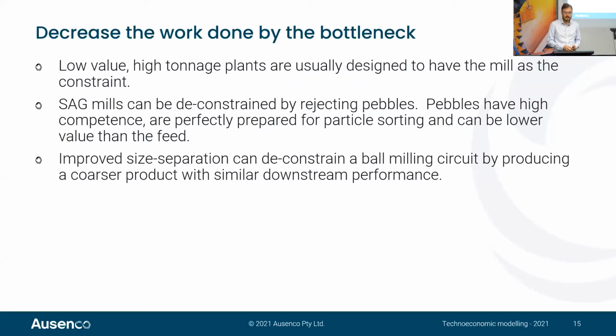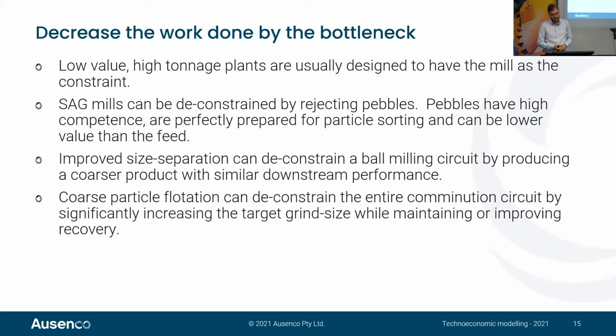And improved size separation can deconstrain the ball mills by producing a coarser product with similar downstream performance. So we can think about fine screening here or other technologies that can be used to produce a product that has a better distribution of material in the floatable size range. But what I'm going to talk about today and concentrate on is really coarse particle flotation. And this can deconstrain the entire comminution circuit by significantly increasing the grind size that can be used, while maintaining or improving, in some cases, the overall recovery.